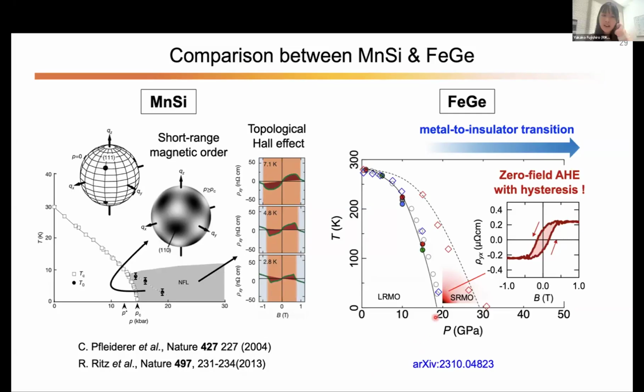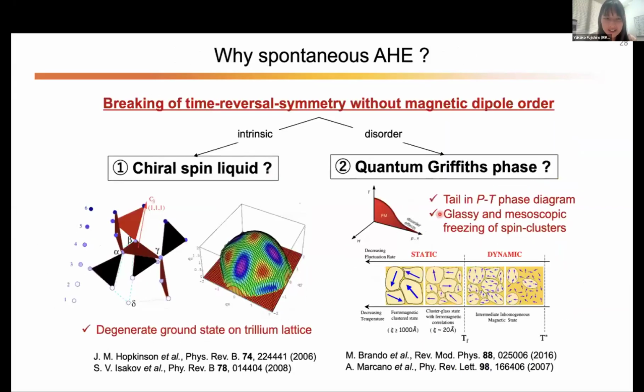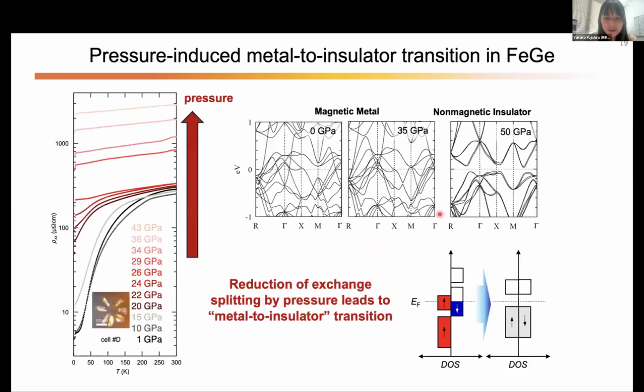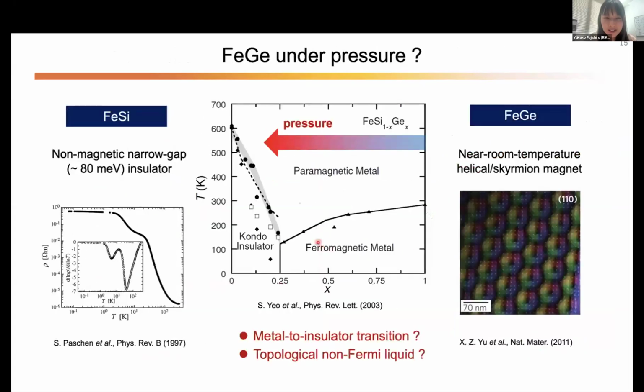So as you say, this is a very high pressure experiment, but if we observe a very interesting phenomenon at this pressure, we can use a chemical substitution method to realize this critical point by a synthesis approach, and then maybe we can obtain the same phenomena at ambient pressure. So I think doing a very high pressure experiment first is very nice, because we can tune the system very smoothly without introducing any chemical disorder, and find a very intrinsic phenomenon first. And then if the phenomenon is really interesting, I think making this chemically substituted material would be very important for practical application.